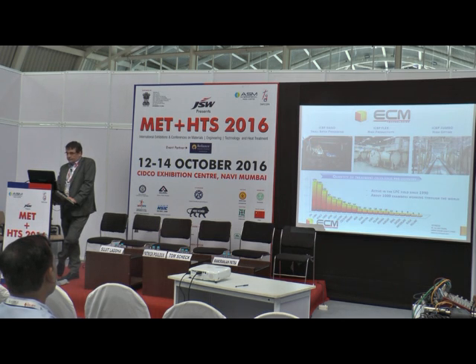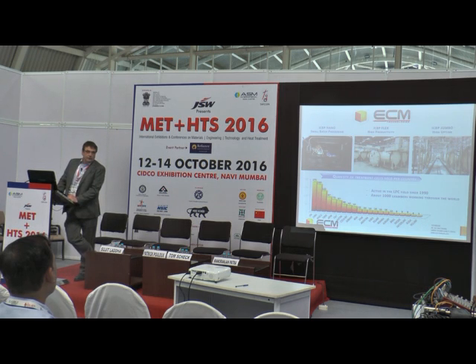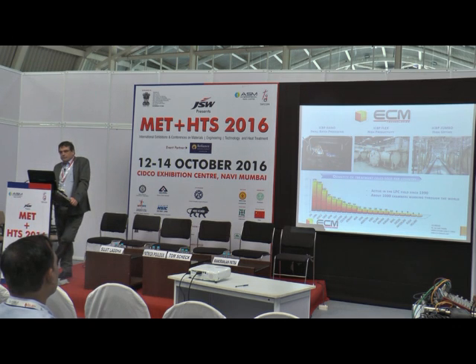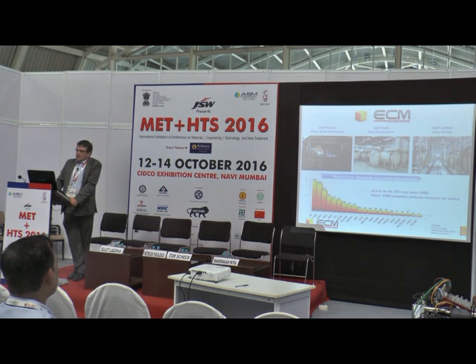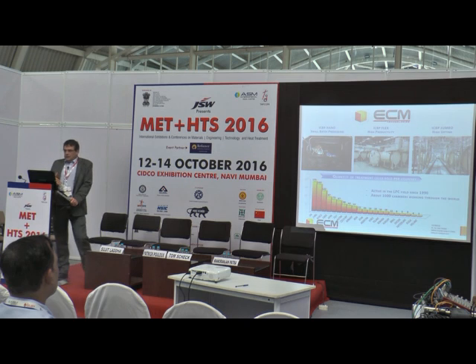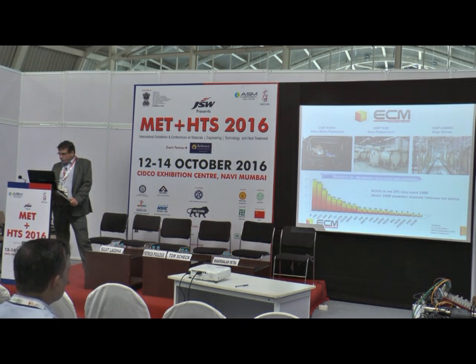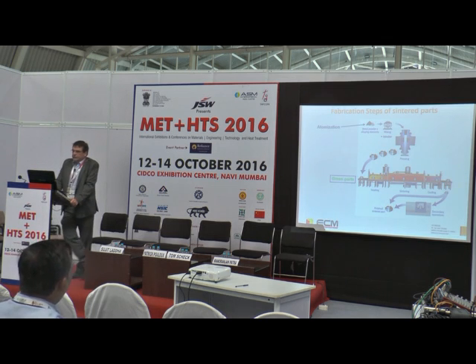So actually, ECM is very well known for what we call ICBP Flex. It's for mass production, mostly for gearboxes. This is a modular system, a complete vacuum process. In the middle there is a vacuum tunnel, and on both sides there are heating cells, up to 8 or 10 heating cells. So it's modular in the sense that you can start with 1 or 2 cells, and when the production increases, add more cells. But today I will explain what we have recently developed for low pressure carburizing or carbonitriding for